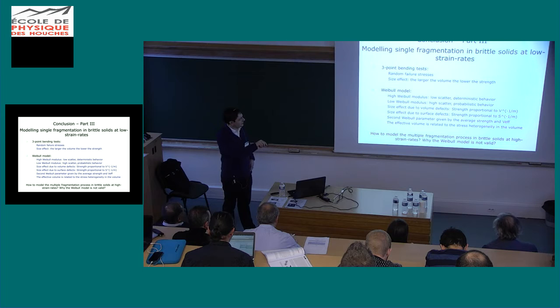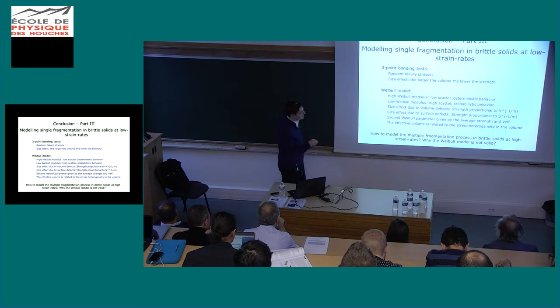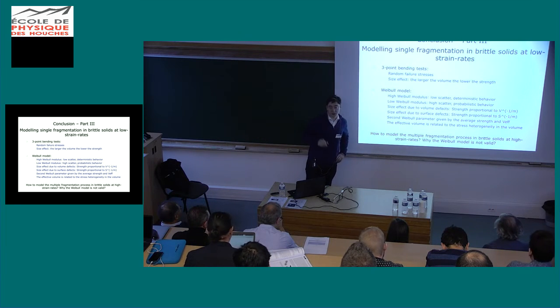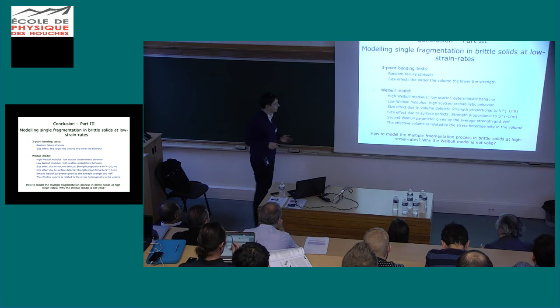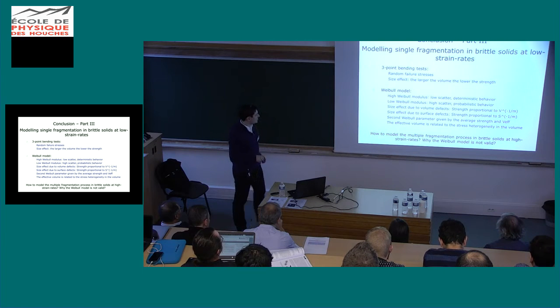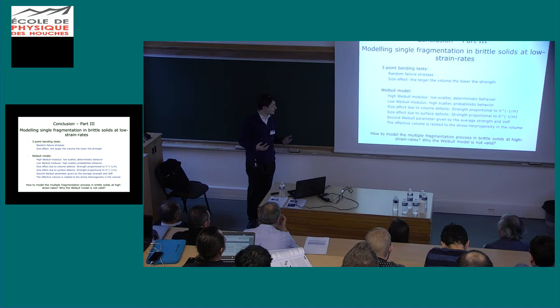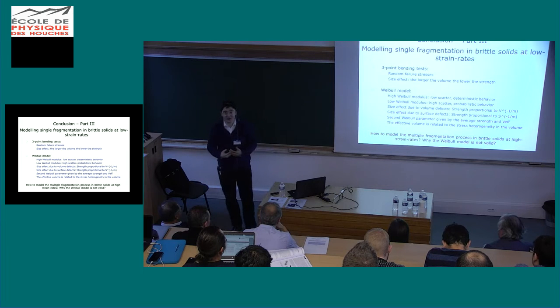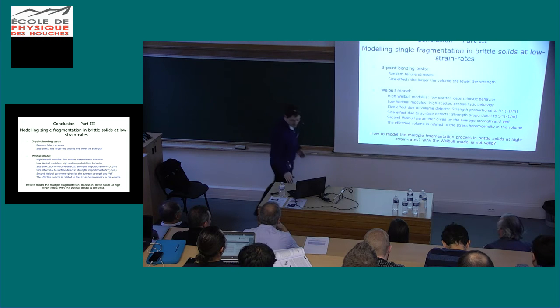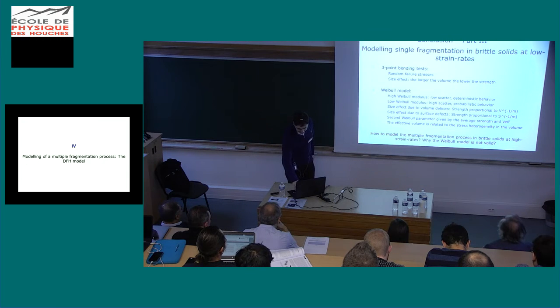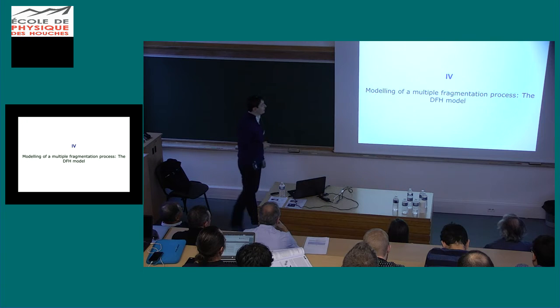In case of surface defects, the Weibull model predicts a strength proportional to the surface to the power minus 1 over m. A second Weibull parameter is provided from the average strength and the effective volume that depends on the Weibull modulus that is known. Okay, so now why is this nice theory not valid at high strain rate? That's a question, and above which strain rate? That's what I want to explain to you.